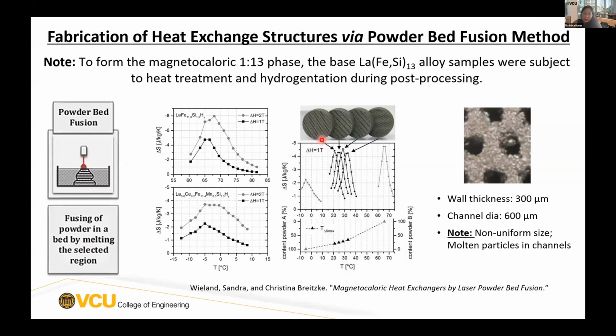At first glance, their net shape samples look really nice. They show high delta S values of about 4 joules per kg Kelvin at a very low field of 1 Tesla. You can stack it up to form a cascaded structure, with wall thicknesses of around 300 microns and channel diameters of 600 microns.